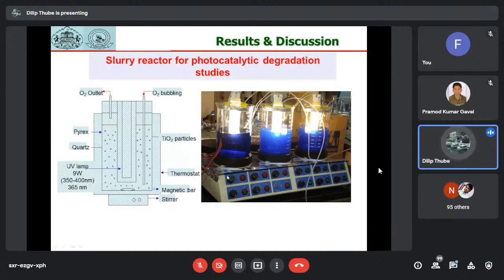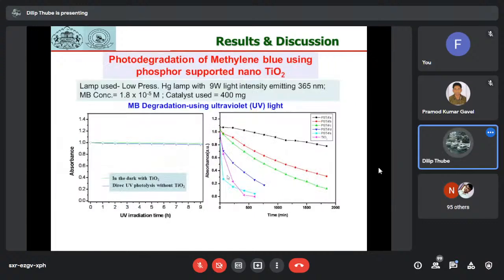If you look at the picture, three various photocatalysts have been employed, and the methylene blue concentration which was kept was the same. After some time, if you look at the color change, the color change is observed in the three photocatalytic reactors to different extents. This indicates that the photocatalytic degradation efficiency of the three different catalysts will be different.